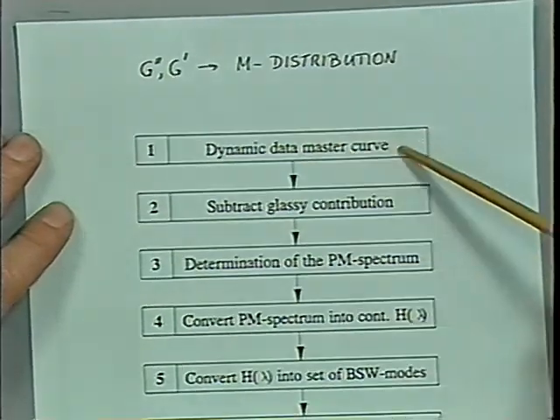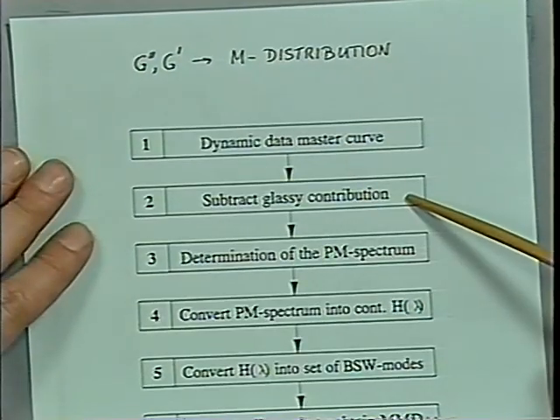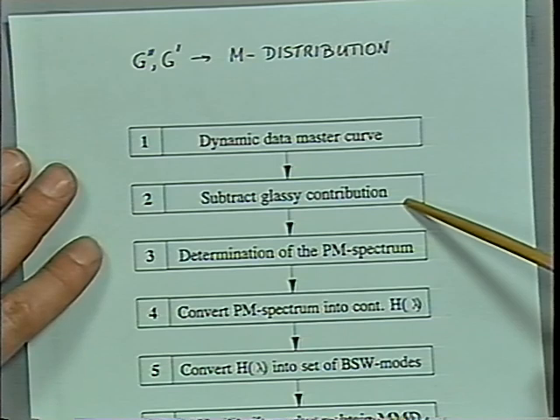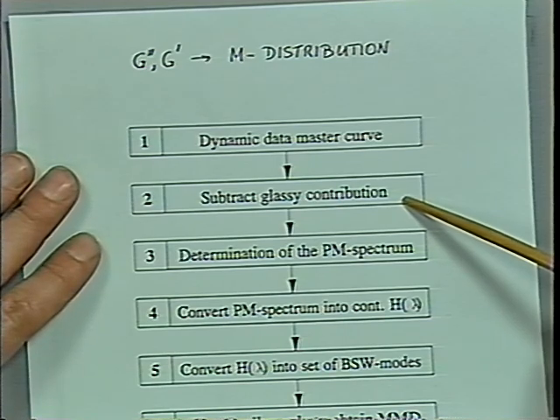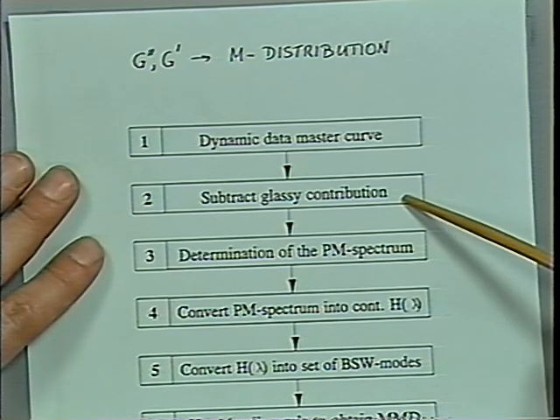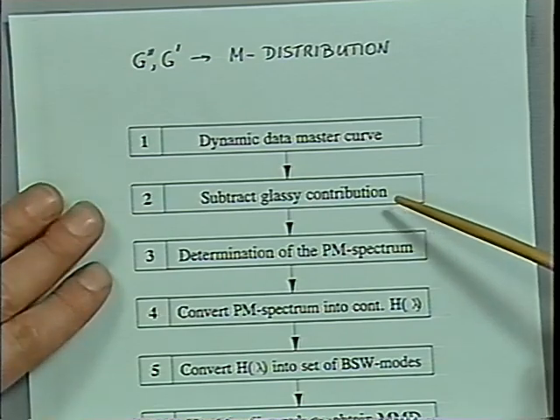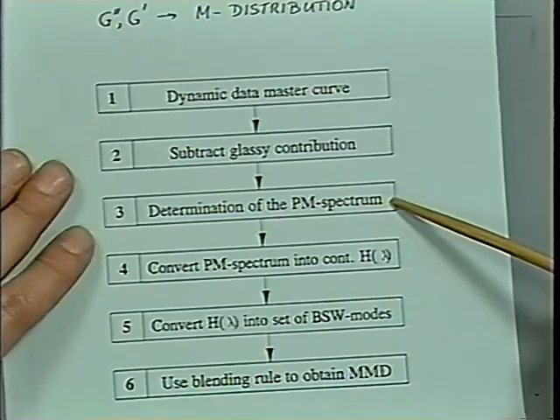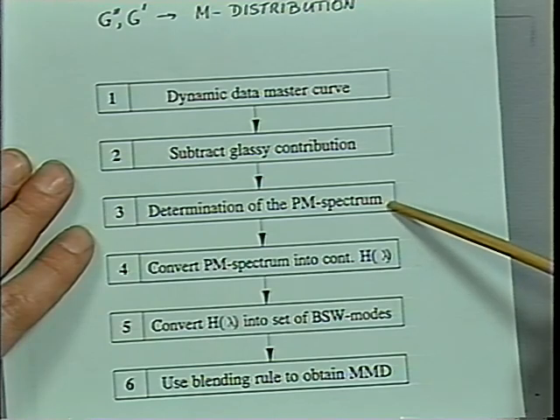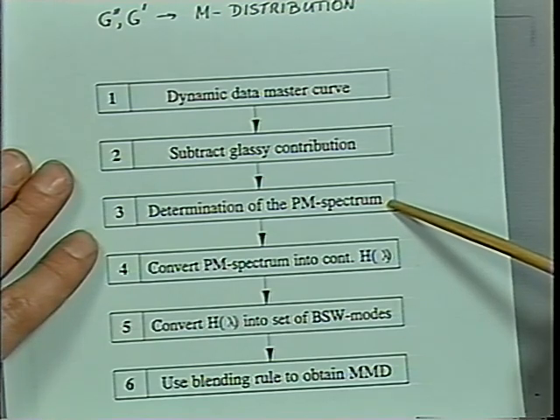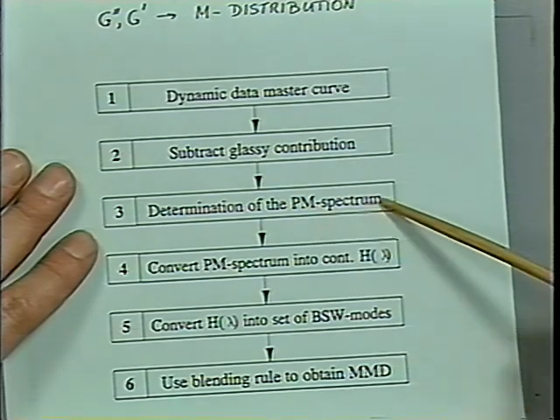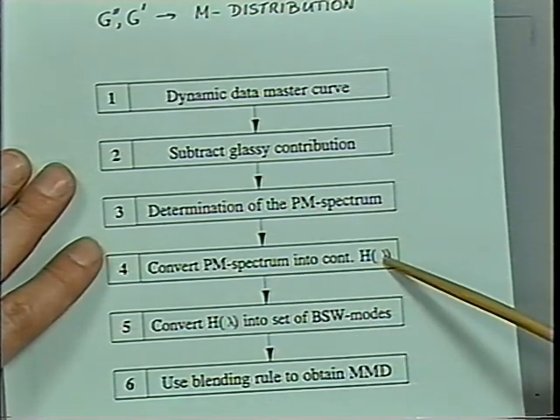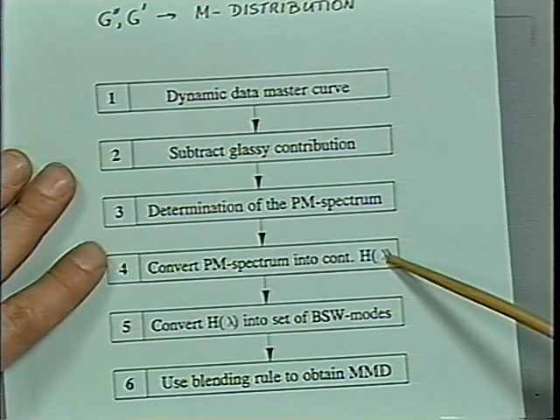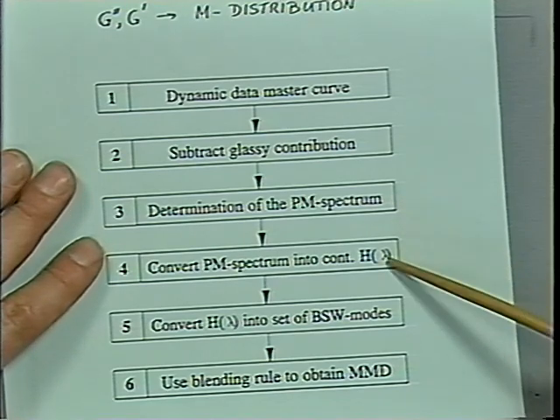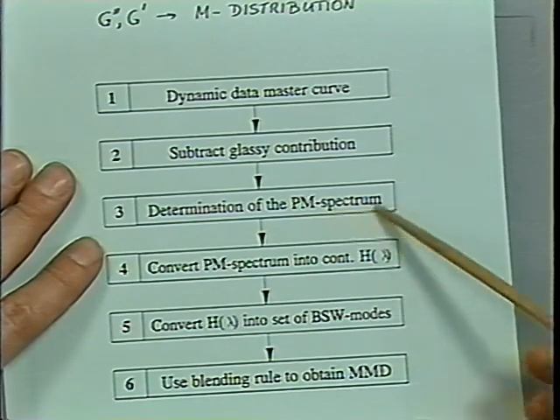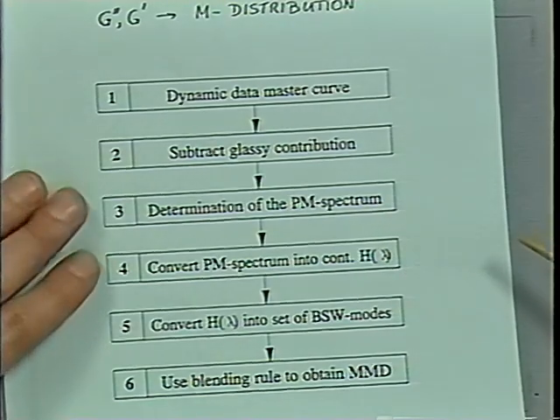So we start with the dynamic data, and then we subtract the glassy contribution, because we only use the entanglement region and the flow regime to determine the molecular weight distribution. And from that, we would determine a discrete set of Maxwell modes. This would be the parsimonious model. And from those Maxwell modes, we can determine the spectrum itself. If those modes are not spaced too far apart, then this is a fairly easy step to do.